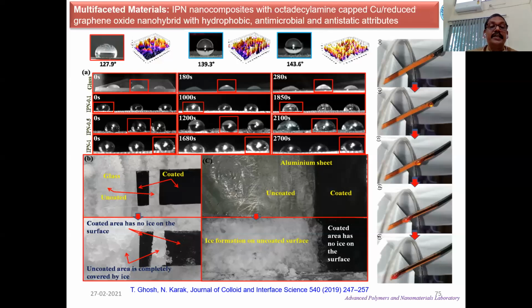Also, because of this hydrophobicity, we have seen that it delays ice formation. In winter regions like Leh or Tawang, running devices and instruments is really very difficult because of ice formation. So when we coat this nanocomposite on a metal plate or glass plate, there is no ice formation, whereas an uncoated surface shows ice formation. Because of this hydrophobic character, this nanocomposite can delay ice formation on the coated surface.